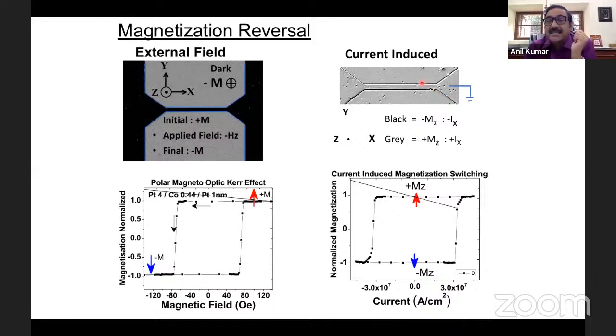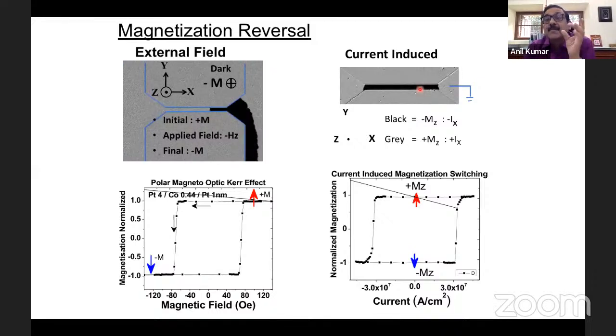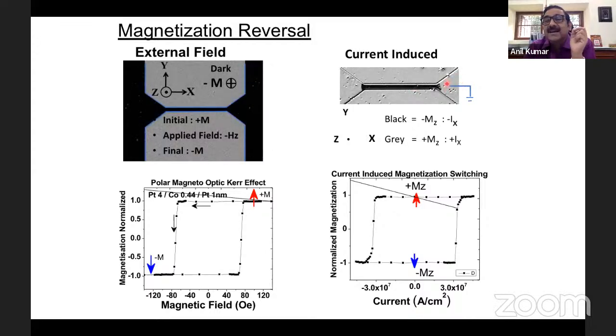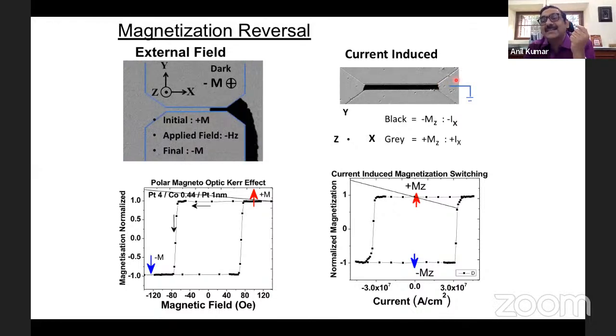So the current density in this region is maximum because this is the lowest dimension structure. Whereas here, the size is bigger. So the denominator is bigger. You need higher current to switch the magnetization in this region.